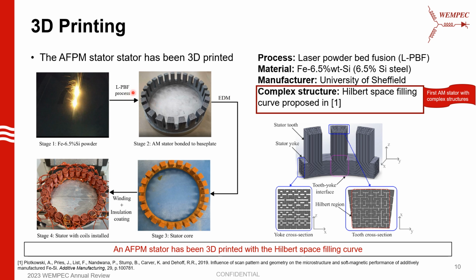This was printed using the laser powder bed fusion process at the University of Sheffield. Once the stator is 3D printed, it comes attached to a base plate, and a wire EDM process was used to separate the stator from the base plate, and then it was heat treated at 1000 degrees Celsius to encourage grain growth and improve the magnetic properties of the stator and structural properties as well.